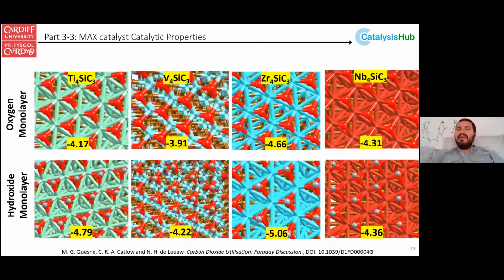Okay, so then we moved on to see what would happen in an oxidative environment. How strong would an oxygen monolayer be? And the answer is very. So we find energies, and this is with reference to an oxygen molecule, not an oxygen atom, that are extremely, extremely exothermic, up to about 4.6 eV per oxygen atom. Now, this actually correlates quite well to what is seen with the MXenes, where it's between 3 and 4. Obviously, it's that elongation of the lattice parameters that slightly destabilizes the surface, but they have a very similar activity to what the MXenes would see, where you'd expect them to be oxidized in these kinds of environments.